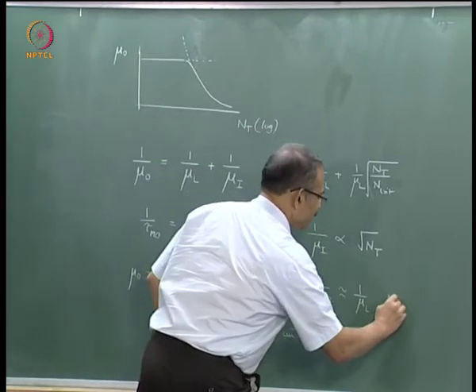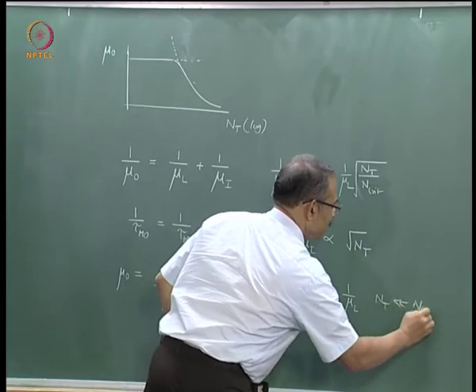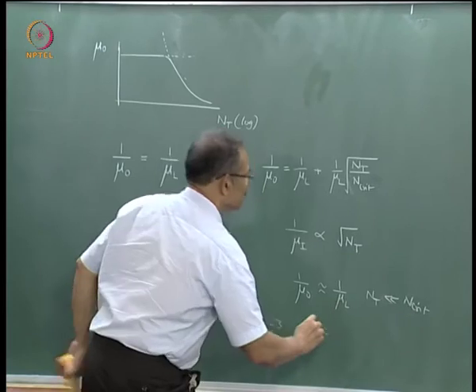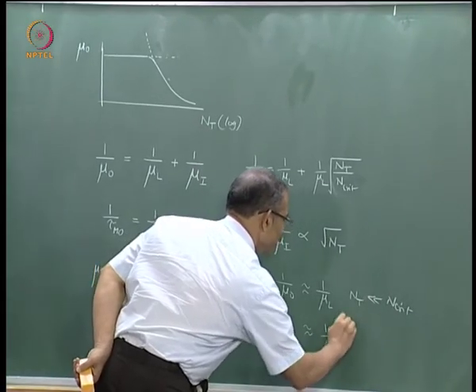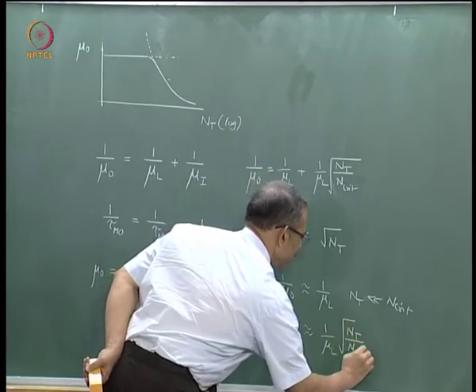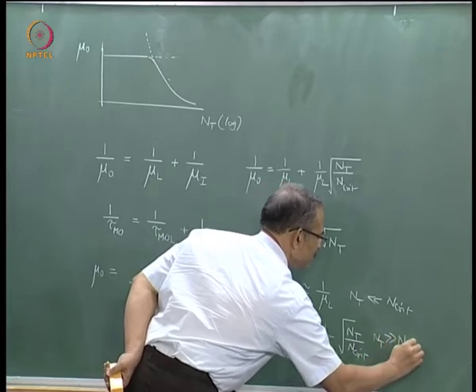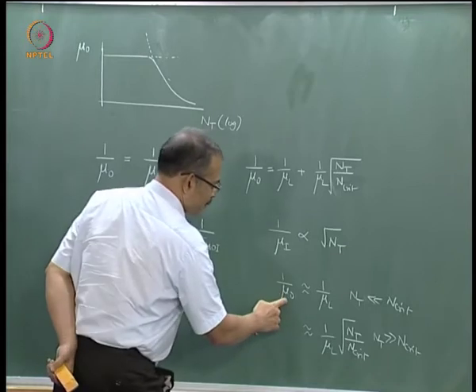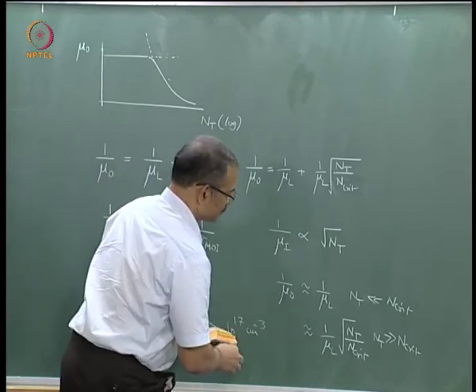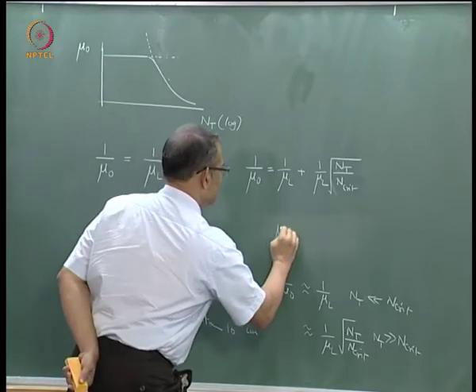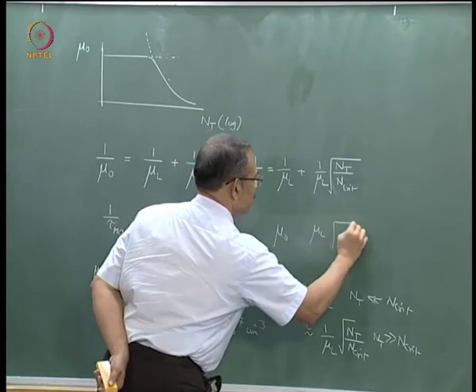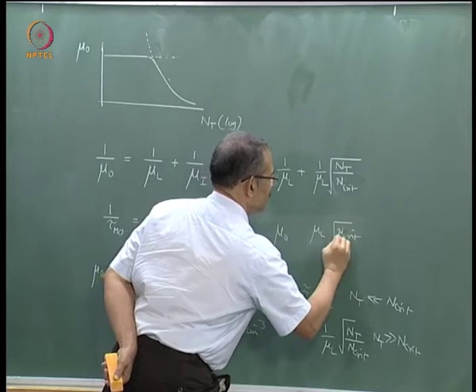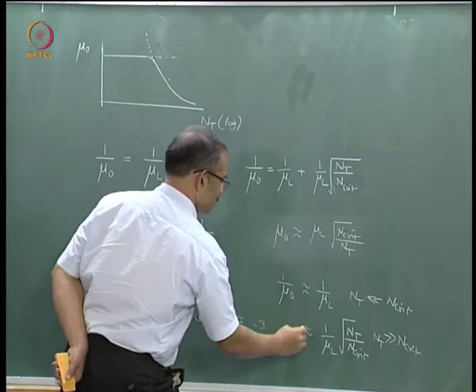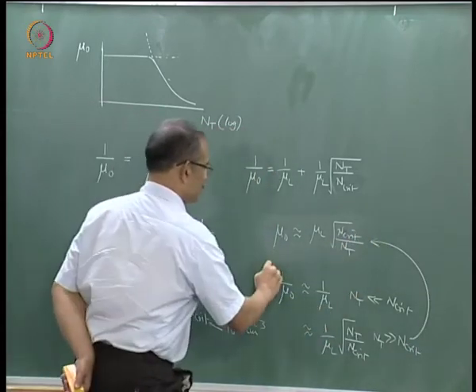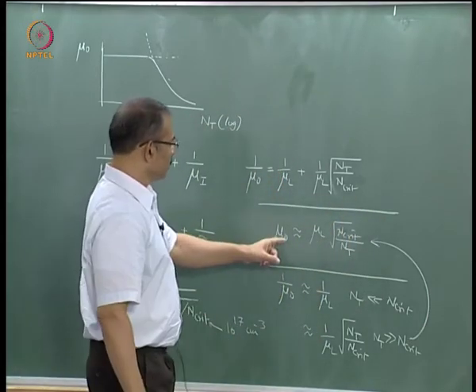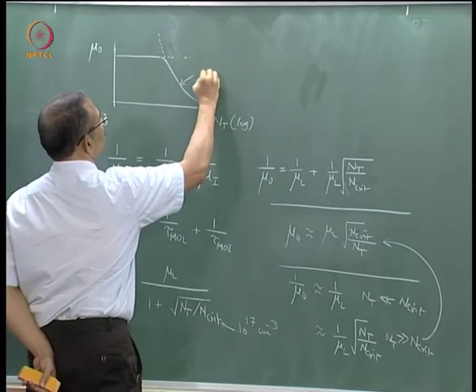And on the other hand, this is for nt small, so nt much less than n critical, and it is approximately equal to 1 by mu L into square root of nt by n critical for nt much greater than n critical. So in other words, if I write for mu naught, I will get mu naught is mu L into square root n critical by nt. So this is this curve. So this curve is proportional to 1 by root nt.